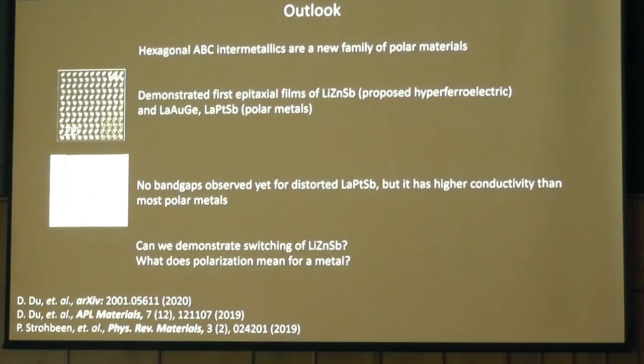Okay, so this work is very preliminary, but I hope I've at least convinced you that these hexagonal intermetallics are an interesting enough set of compounds to study, in addition to all the great work on oxides, in that these are new polar compounds that can perhaps host hyperferroelectricity and perhaps other phenomena related to magnetism and topological states that are stabilized by polar structures. We've demonstrated the first MBE growth in this class of materials. We've done it with lithium zinc antimony, which was one of the proposed hyperferroelectrics. We've also done it with lanthanum gold germanium and lanthanum platinum antimony, which are these polar metals.